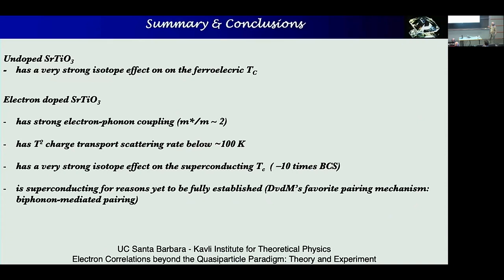It's not there if you don't put in the isotope, the oxygen 18, and it becomes ferroelectric if you do. There's a very strong electron-phonon coupling, which gives you a mass renormalization of a factor of 2 for the electron-doped strontium titanate. There's a T-squared charge transport scattering below 100 Kelvin that is sort of understood, but there are a few loose ends also in Dimitri's story.